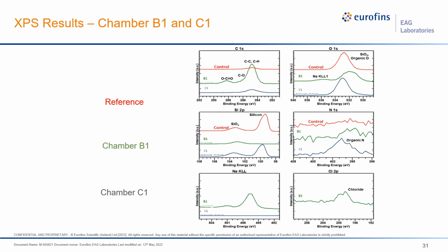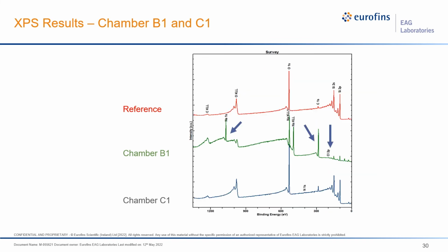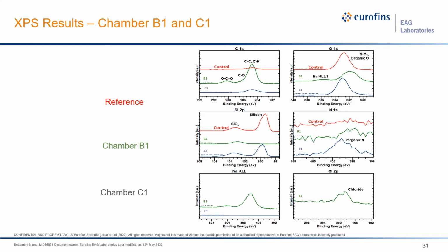Now, these are high resolution scans, so we can take a scan like these, where we're going from 0 to about 1300 eV for binding energy. Then what we can do is go down to a much smaller scan. Say for the carbon 1s up here, we're going to go from 280 to 292. And this scan allows us to get much more resolution on the data.